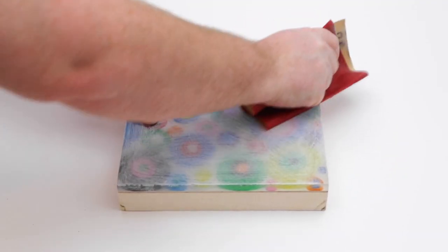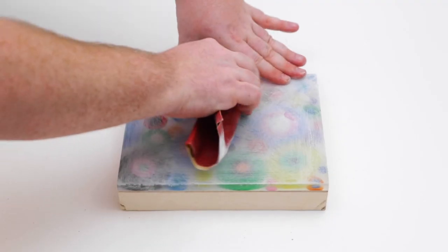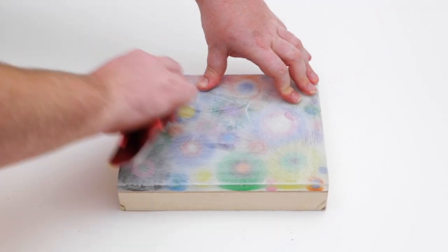To fix the sticky spots, you need to scrape away any of that unmixed material, and secondly you need to sand down any of the cured parts with 80 grit sandpaper to make sure that there's enough tooth to adhere that second layer on top.